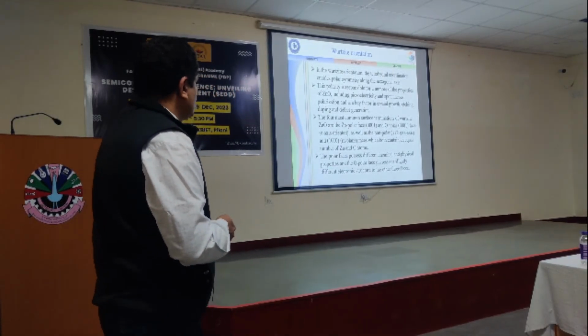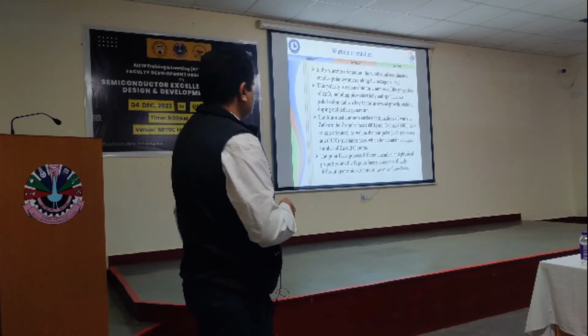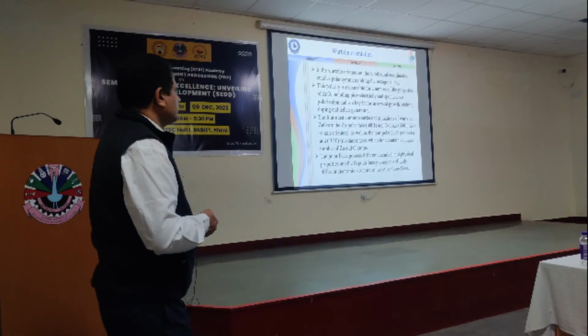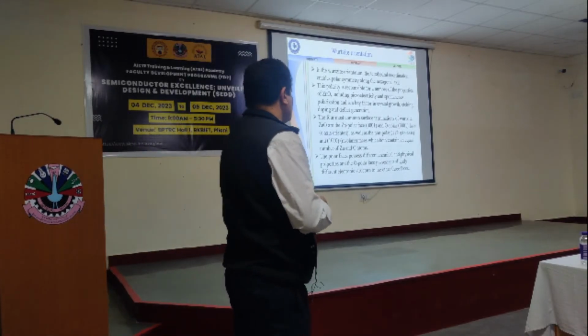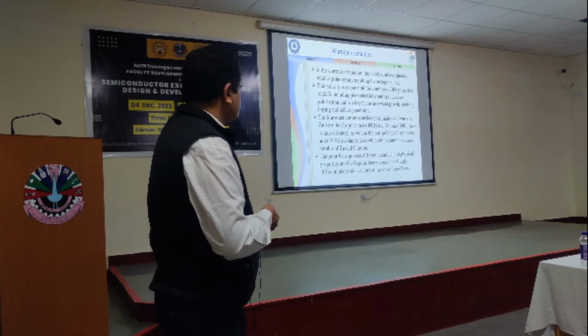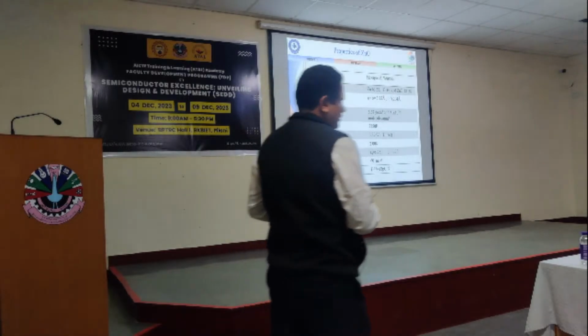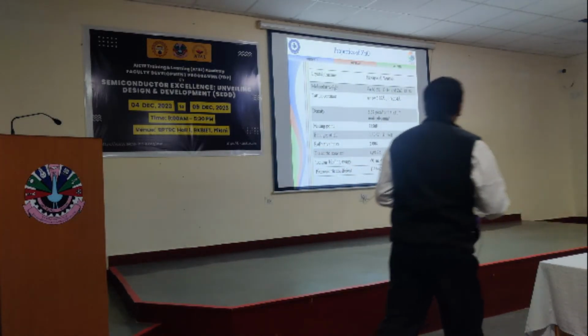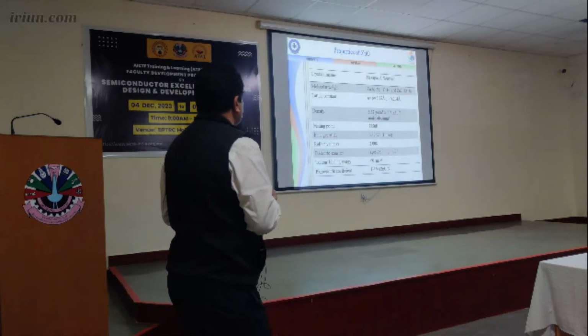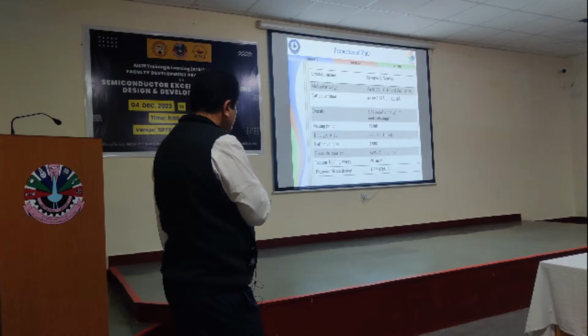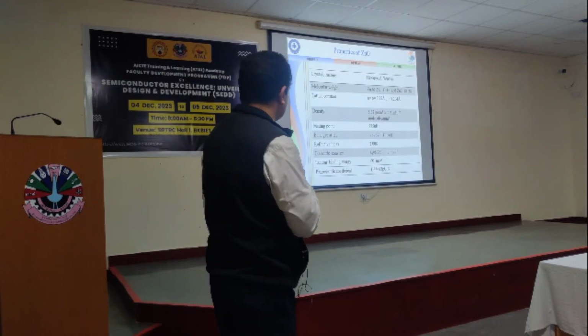Wurtzite has tetrahedral coordination and polar symmetry along the hexagonal axis, with the zinc face (001) and the oxygen face (00-1), C-axis oriented. The polar face possesses different chemical and physical properties, and a slightly different electronic structure from the other three phases. The cubic phase does not have piezoelectricity. Zinc oxide has a hexagonal crystal structure, with lattice constants given for the C-axis orientation. Its band gap is nearly 3.3 electron volts and it has a piezo coefficient of 12 picocoulomb per Newton, D33.